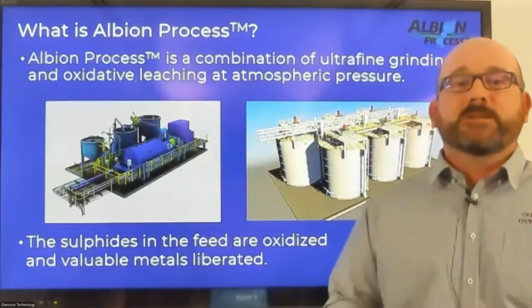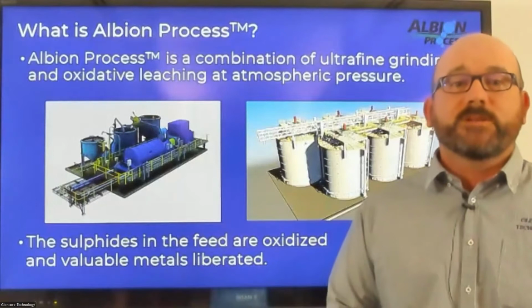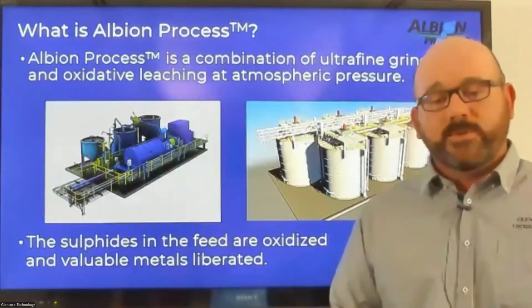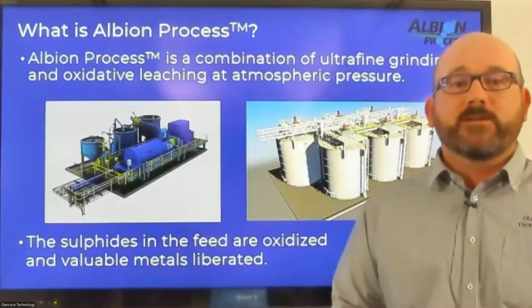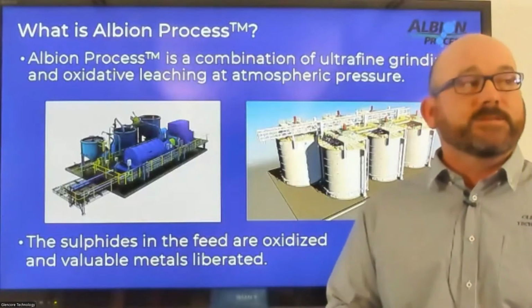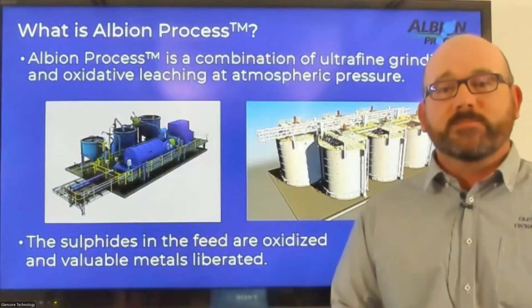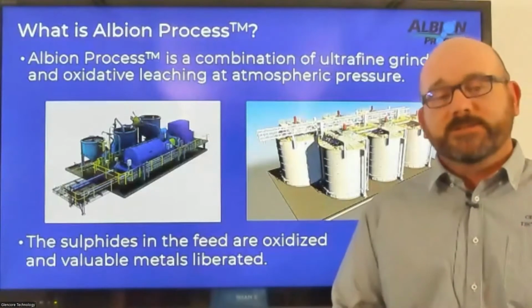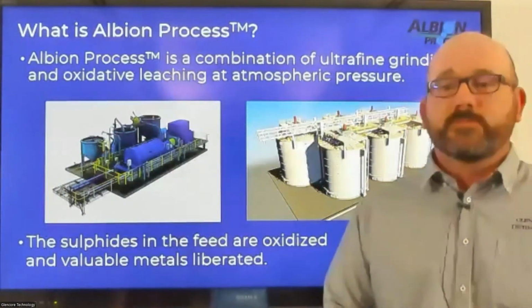Also in the Albion process, if you do have base metals that are associated with the gold, we can look at using our acid Albion process under different conditions, so we can liberate the base metals initially, and then still look to recover the gold from the tailings.